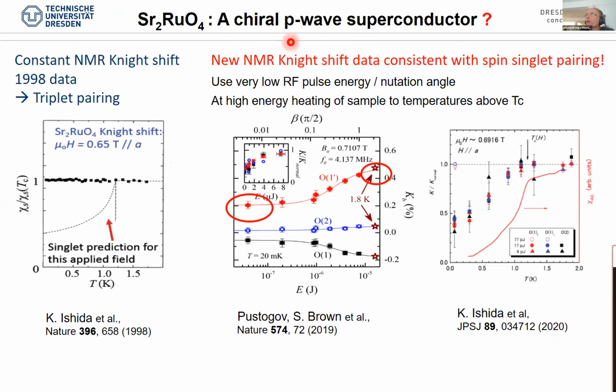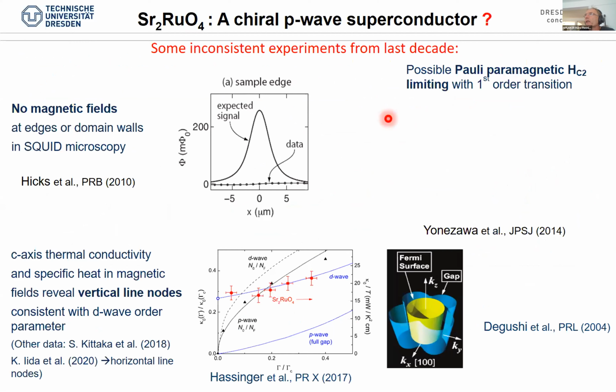The problem, of course, with strontium ruthenate is that in the last decade, I would even say, this chiral p-wave state has been questioned by several experiments. The last one is really the very important experiment by Stuart Brown's group, and also confirmed by Kenji Ishida, that now in strontium ruthenate there is this Knight shift change or reduction of Knight shift below Tc, so that it is definitely a spin singlet even pairing state. And there were indications that the p-wave state is not the correct one already during the last decade.